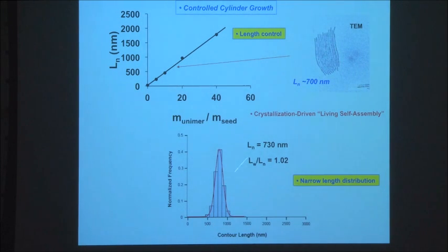If you look at the dispersity and length, it's a very narrow length distribution, you get a very narrow polydispersity index. So you get narrow length distribution. These are both characteristics of a living polymerization. So this is really like doing a living polymerization on a different length scale, and we called this process crystallization-driven living self-assembly because of the analogy with living covalent polymerizations.